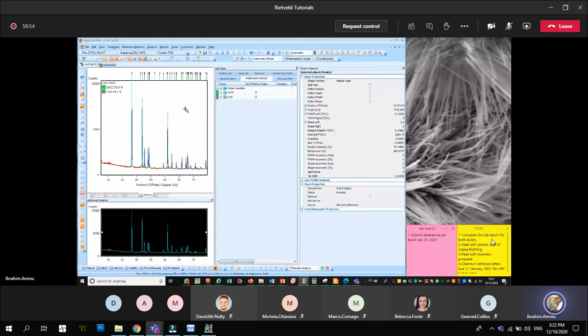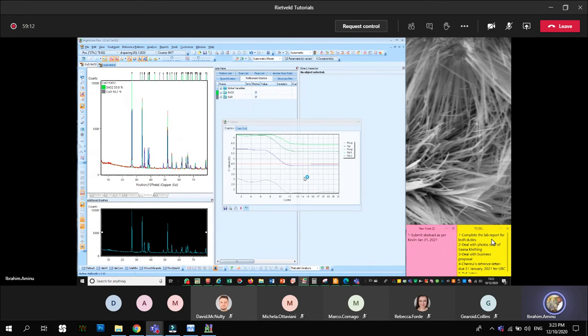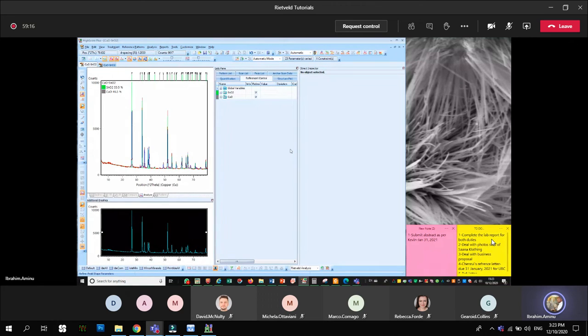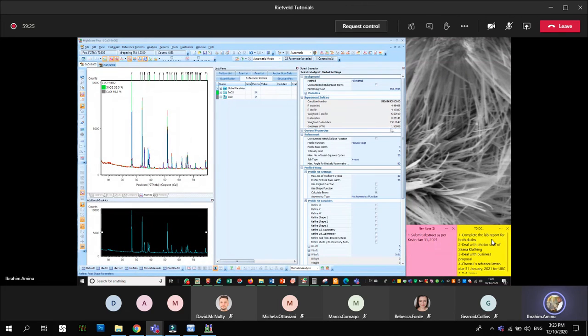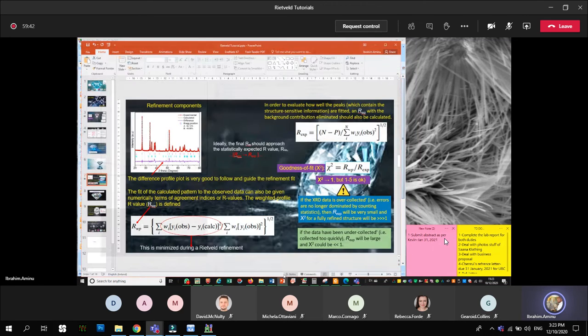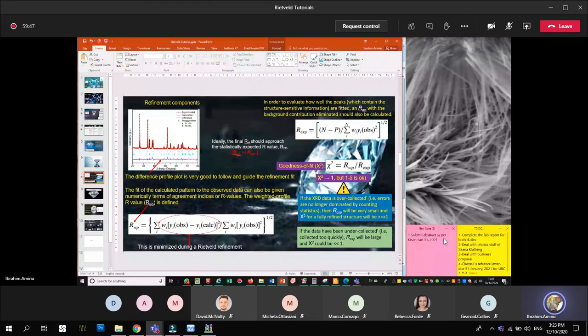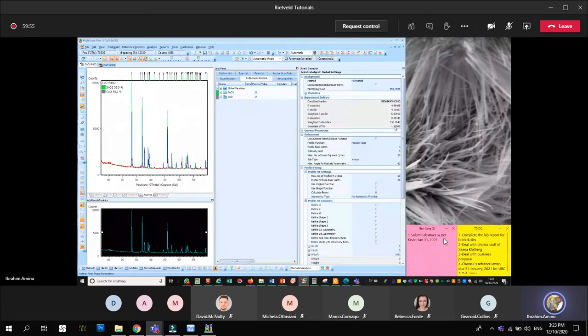So you can go to size strain analysis, click that again, then it will refine. Depending on your computer and the number of phases, this can take a long time or a very short time. Once you click that, you check the goodness of fit, you see it has reduced from 2.4 or so to 1.5, and your Rwp, which is 4.48, is almost approaching the 5.5, which is the expected value. Remember this statement here: we should try to reduce goodness of fit closer to 1, which is better. So we can see it is quite okay. You can continue to do this and improve.